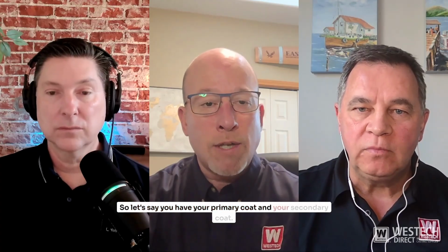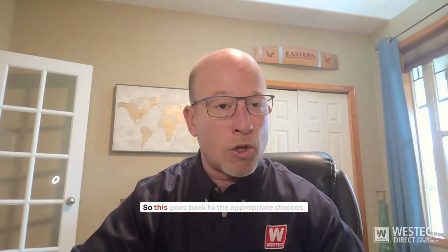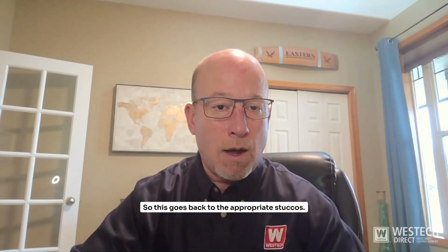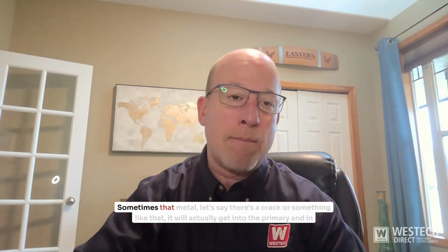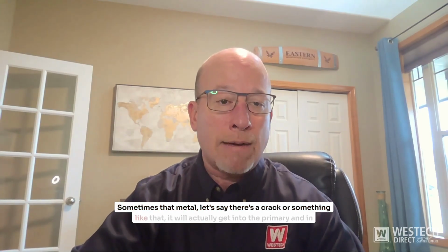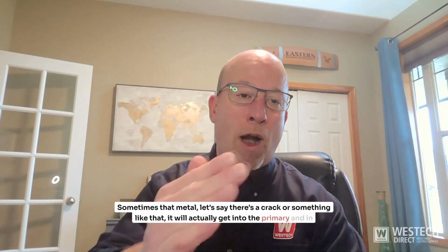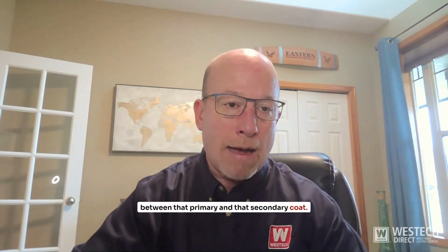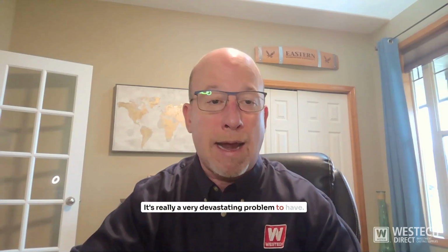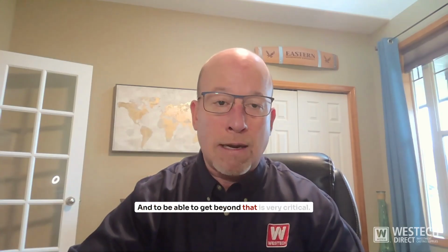Spalling is when metal penetrates between two coats. So let's say you have your primary coat and your secondary coat, and you do not have a good transitional sand. So this goes back to the appropriate stuccos. And this is just one example. Sometimes that metal, let's say there's a crack or something like that, it will actually get into the primary and in between that primary and that secondary coat. It could leave a scab, a subsurface scab of ceramic as a result of it. It's really a very devastating problem to have, and to be able to get beyond it is very critical.